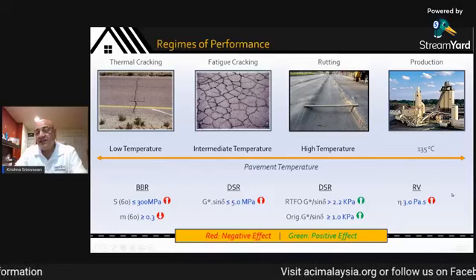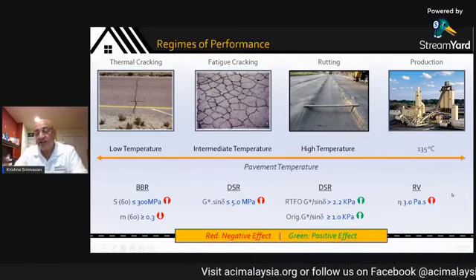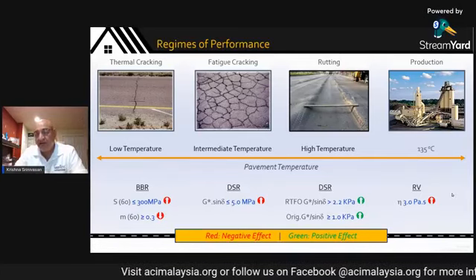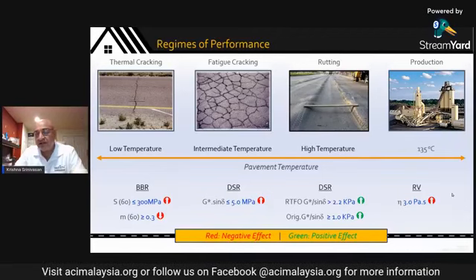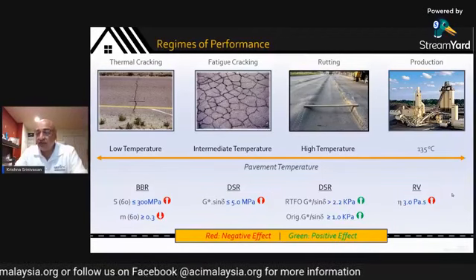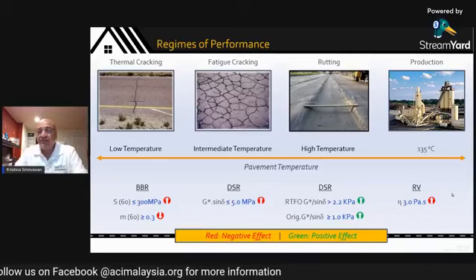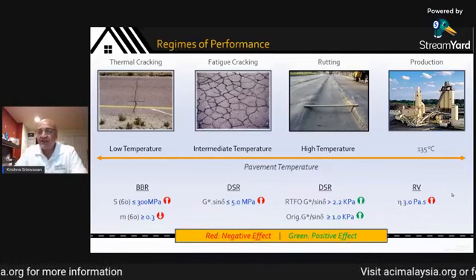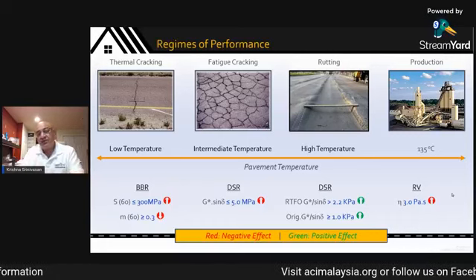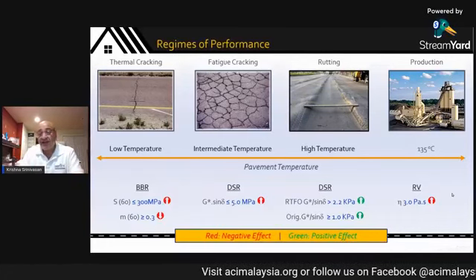Finally, here are some parameters that are used to characterize the bitumen needed in a plant environment. You're looking at rotational viscosity. And as you can imagine, if you extract the bitumen from aged RAP, it is stiff, it is brittle, the viscosity is too high to be able to be processed satisfactorily in a plant.